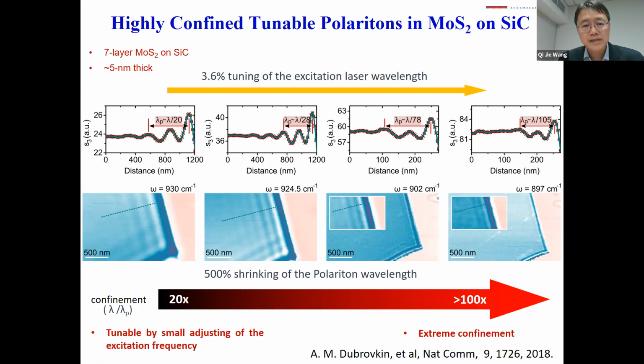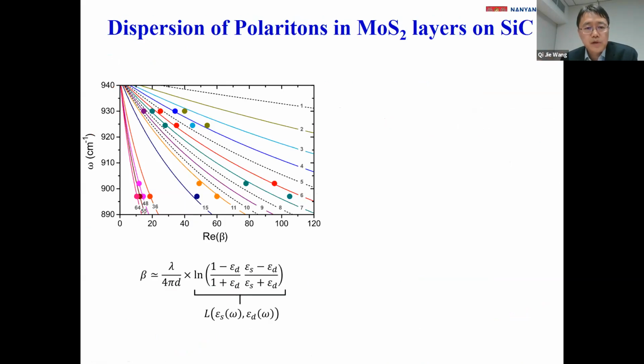And we also see that by slightly tuning the excitation laser wavelengths by a few %, we can control or manipulate the confinement factor of Phonon-Polariton, from 20 times up to 100 times. So this gives us the flexibility of tuning through changing the excitation frequency. And then we measured several different devices with different thickness, and we plot this dispersion curve as compared to the theoretical predictions.